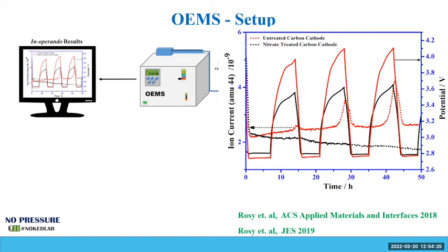So what we have shown here is two properties. This is not a work that I wanted to focus on today, but because you asked, you can see that the voltage is lower for the coated one. This is better. It means a healthier oxygen reduction reaction, and it is also lower in voltage for the oxygen evolution reaction. So both are improved. We improve the redox reaction of the oxygen, but we also suppress the evolution of the undesirable gases. This is not coating. This is surface treatment with lithium nitrate. So it's a different thing.